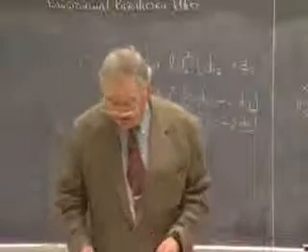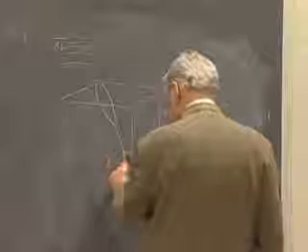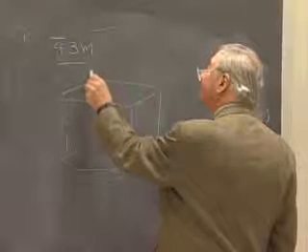One other piezoelectric modulus is in the problem set, 4-bar 3M. This is the structure of sphalerite and a lot of the compound semiconductors. This is not in the notes, but if you try the problem, what you find is, again, highly anisotropic behavior. And this is the direction of the unit cell of the crystal. You find that the piezoelectric response is a series of very sharp lobes, positive and negative, going along the directions of the body diagonal, namely the 1, 1, 1 directions in the crystal.